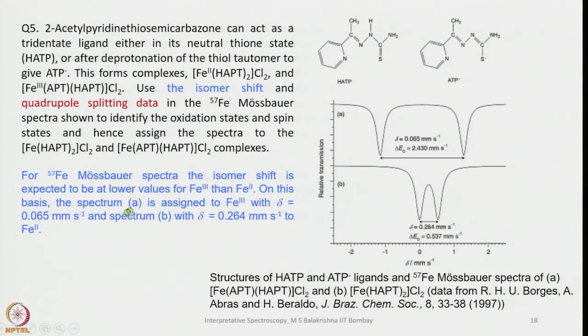On this basis, spectrum A is assigned to Fe3+ with an isomer shift delta of 0.065 millimeters per second and ΔEQ of 2.430 millimeters per second, and the second one is assigned to Fe2+ having delta equals 0.264 millimeters per second and ΔEQ equals 0.537 millimeters per second.